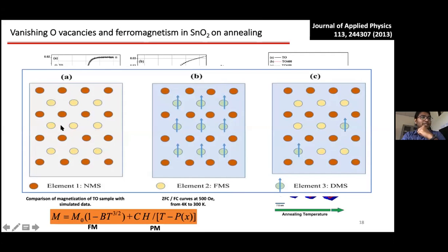Okay. So there wouldn't be any spins, and it would show some kind of a diamagnetic behavior. If there are spins present at regular periodic sites, like a regular ferromagnetic system, you will have spins in a particular order. They will have some exchange correlation J, which will give rise to ferromagnetic ordering. However, if there are vacancies and they are trapping electrons which can have unpaired spin, which can give rise to some kind of a moment in the sample, people proposed a bound magnetic polaron.